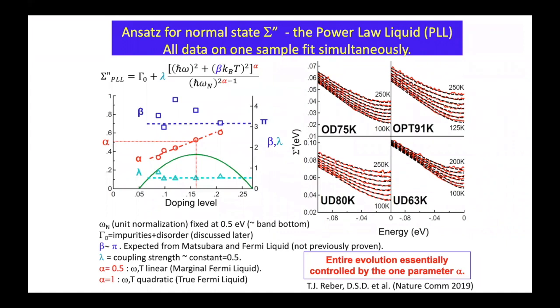We fit to an ansatz for what sigma double prime should do. We call this the power law liquid phenomenology. As a function of frequency or temperature, it's sort of an internal quadratic thing, but then raised to some exponent. That's our power law. And with something that connects the two scales, an offset, a coupling term, and then I'll tell you about this later. Here's the data, which is the same as on the last slide.